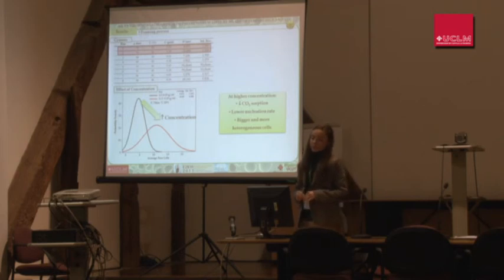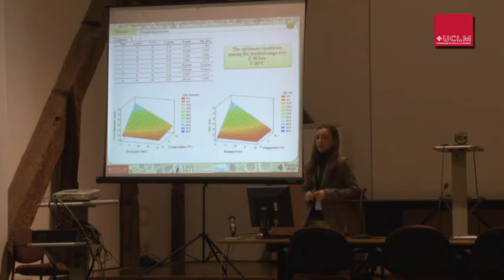Finally, we determine the effect of concentration on the diameter and its standard deviation, and we observe that although it isn't significantly influenced, we can see that at higher concentration, the carbon dioxide sorption into the polymer solution decreases. So there is a low nucleation rate that is responsible for the creation of bigger but more heterogeneous cells. According to these results, we performed the statistical analysis, and we can observe that the optimum condition to get the smallest and most homogeneous pore cells was obtained at 90 bar and 30 Celsius degrees.